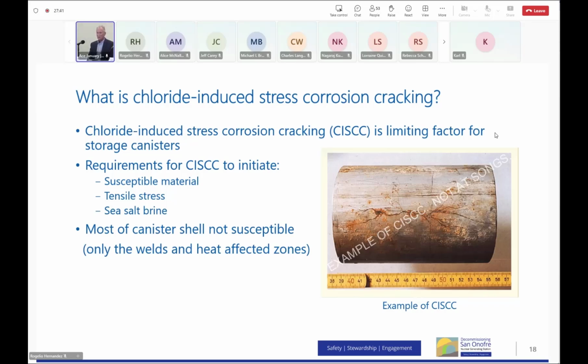Now, to get CISCC, and I think you're going to hear this several times tonight, you have to have susceptible material, you have to have a tensile stress, and you have to have chlorides. In this case, what it says here, sea salt brine, what that means is chlorides. The chlorides have to be wetted. They can't be dry chlorides. We have dry chlorides on all our canisters. There is dry salt on all our canisters. In a seaside environment, you're going to have salt everywhere. We don't try to prevent salt. Just want to make that clear.